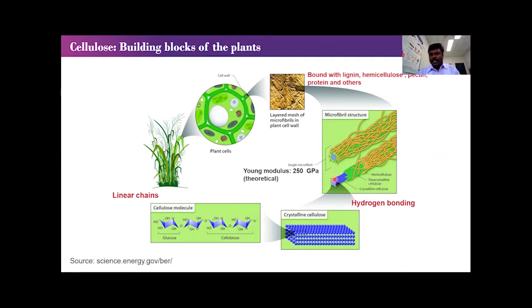If you deconstruct back into this nanoscale, we can exploit the mechanical properties it offers, and also the chemical functionalities it has: the OH groups, and it's a linear polymer. We can exploit these functional groups and the mechanical properties. It also has really low density in comparison to other inorganic materials. When you go to the nanoscale, you increase the surface area, making more hydroxyl groups available for